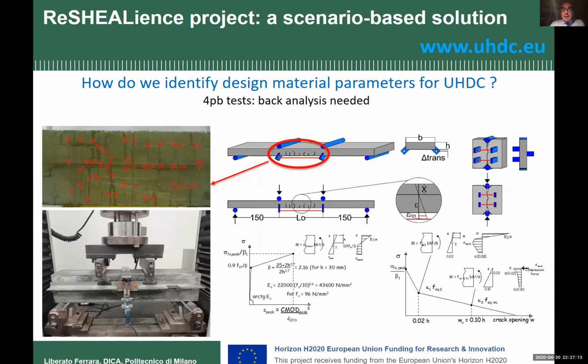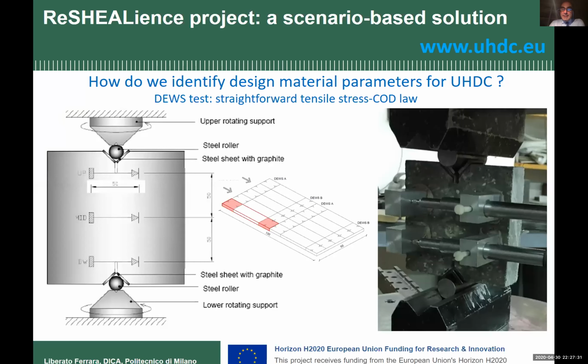Then from the results of flexural tests, through the laws of fracture mechanics, we were able to identify the constitutive relationship in tension, which was used in the design. We also developed a specific test methodology, which we call a double-edge wedge splitting test, to directly identify this law. If you make a bending test, you need a back analysis to identify the law, whereas we needed something fast and effective. So we developed this test, basically a modified Brazilian splitting test. We introduced notches to localize cracking, which is also sensitive to the alignment of the fibers.